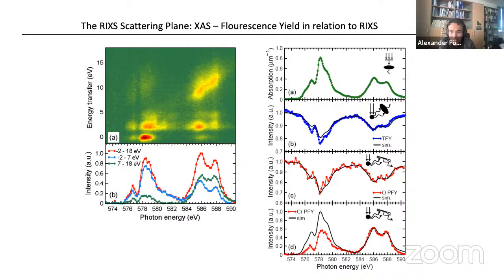And so I think there are really two lessons learned. If you want to do a comparative study, for example, if you have an electrochemical cell and you do a cyclic voltammetric measurement, I mean, you cycle the cell, and then you measure NEXAFS as a function of voltage, you see the relative changes very well, right? You can very easily do a comparative thing. You've got to be super careful if you want to really count the number of species. For that, just doing a fluorescence measurement is not going to do the thing. You really have to work on getting to a Lambert-Beer condition.